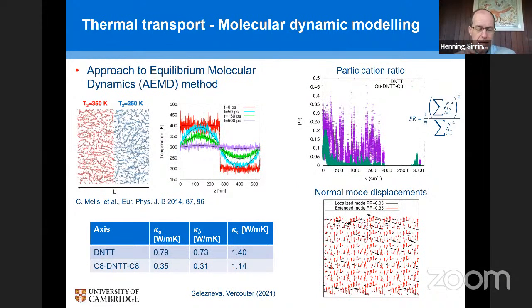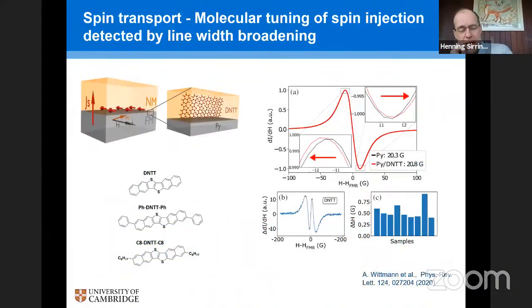It turns out that essentially what happens here is that the so-called participation ratio, which is a measure of how delocalized the normal modes are, is reducing significantly when you substitute with the alkyl chains. So the unsubstituted molecule has more delocalized phonon modes, whereas the attachment of side chains suppresses this delocalization, and the phonon modes become significantly more localized, and as a result the thermal conductivity is reduced. As I said, I just wanted to mention in passing that we're also interested in thermal properties.